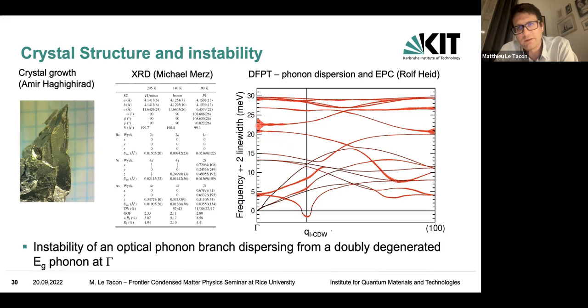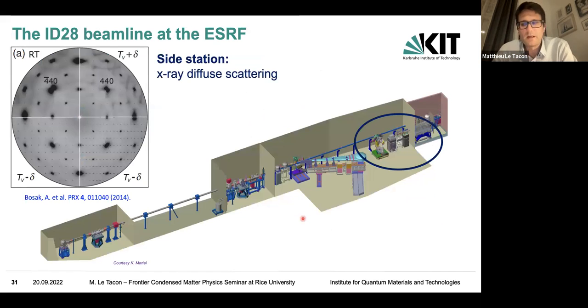I haven't shown that, but if you dope the system, it displays a nice little Fano asymmetry, which is in line with the notion that this is the main contributor to the electron-phonon coupling. So that one is not the one which has the strongest electron-phonon coupling, yet it displays a clear instability. So we wanted to investigate the dispersion of that mode,